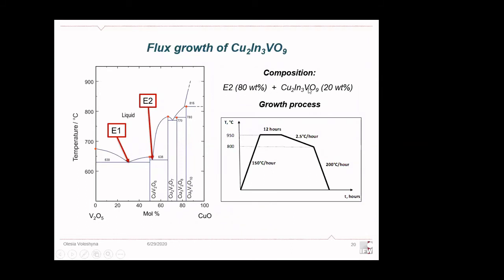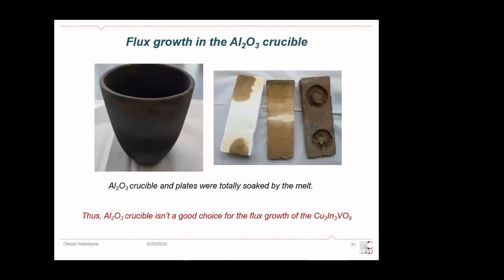The composition you can see on a slide, and the growth process was carried out like fast heating, then holding for the proper time at temperature, then slow cooling down to promote crystallization, and rapid cooling to the room temperature.